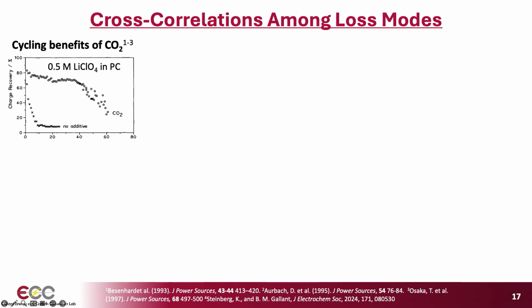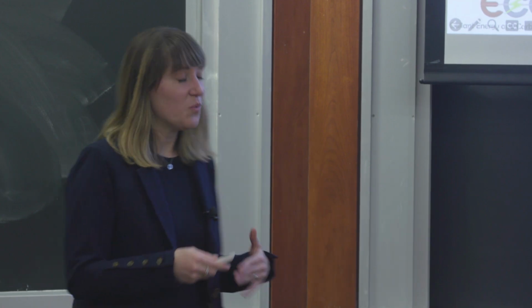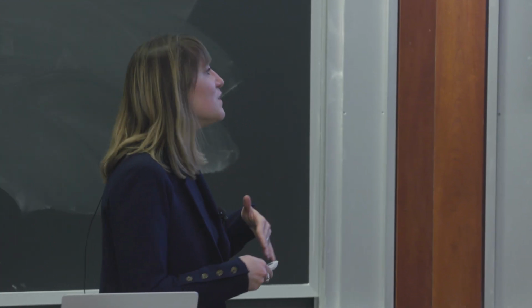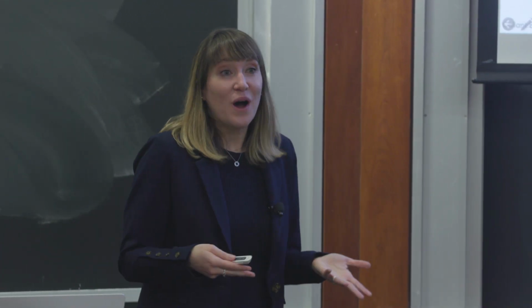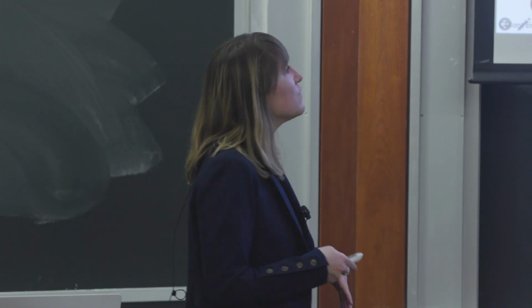So beyond the analysis we've done so far, we can also start to look at cross-correlations among loss modes. Here I will show you this through the lens of an example based on some data that had been puzzling and interesting to the field for a number of years, which is that if you take some classical carbonate electrolytes and you add CO2 gas as an additive, it can actually dramatically improve the lithium cyclability. So we were interested in understanding, first of all, does that apply to an expanded set of electrolytes? And also, why would that be the case? Why would adding CO2 improve cyclability?